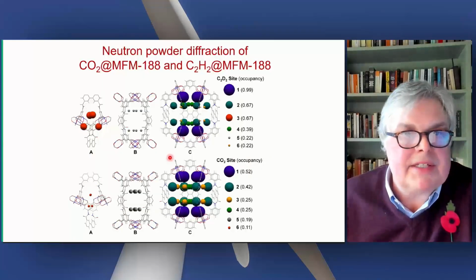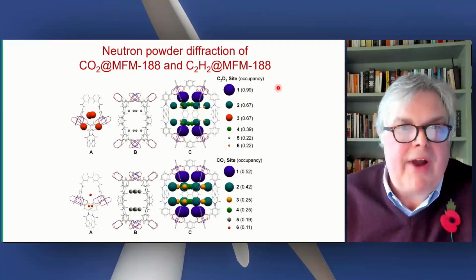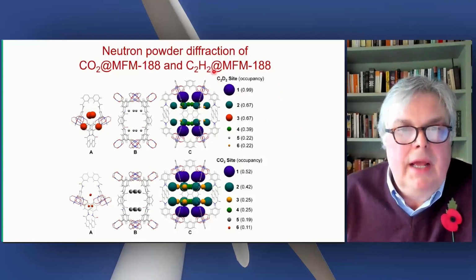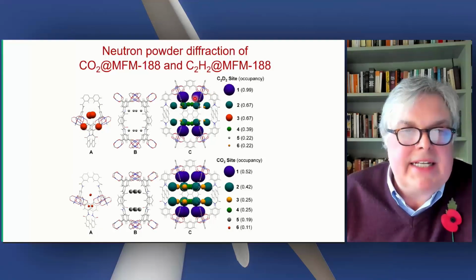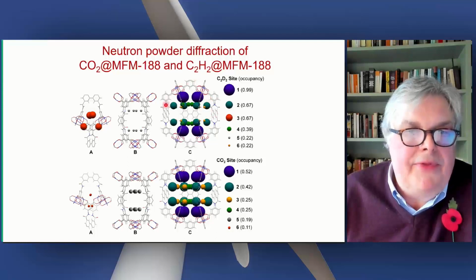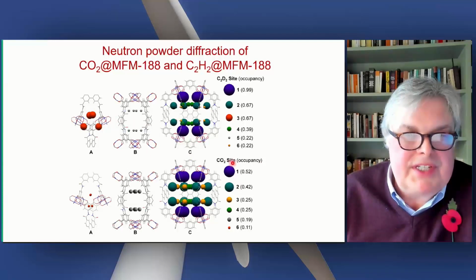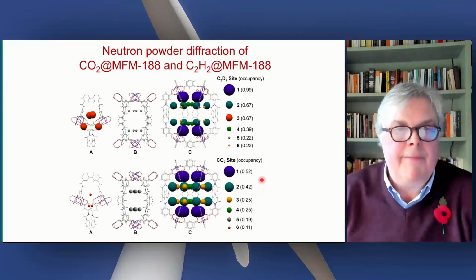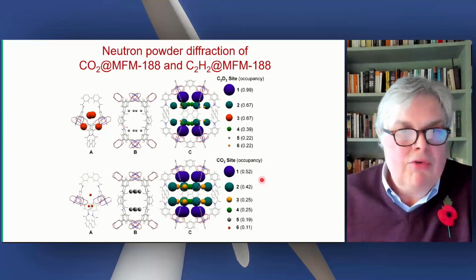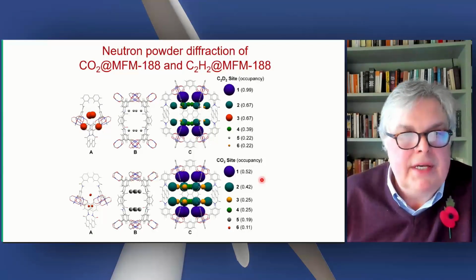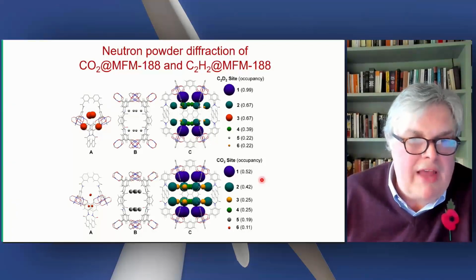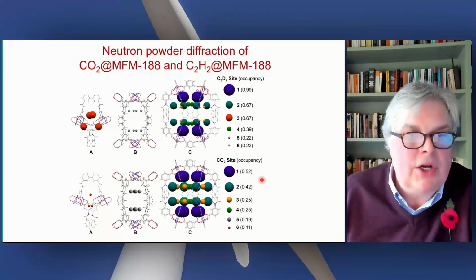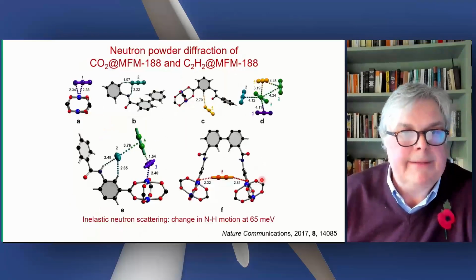And the reason for this is shown in these neutron powder diffraction structures from ISIS. We can locate the acetylene binding sites. These are at the paddle wheel, copper paddle wheels, but also you will see that this particular pore fills preferentially to these other ones. We can nicely compare this with CO2. We have the CO2 binding sites there as well. So that gives us really very nice understanding of how this host-guest chemistry works, what are the driving forces for good capacity, and indeed, what are the drivers for poor or low capacity.